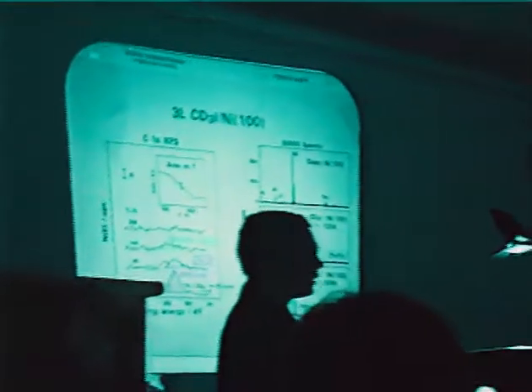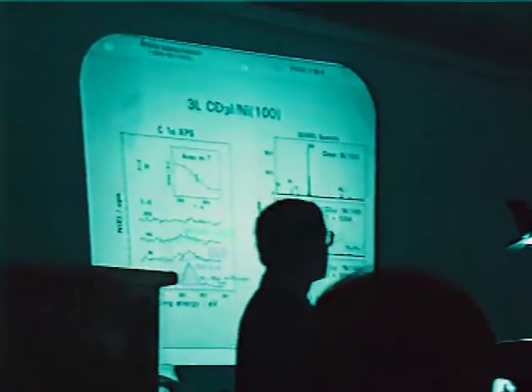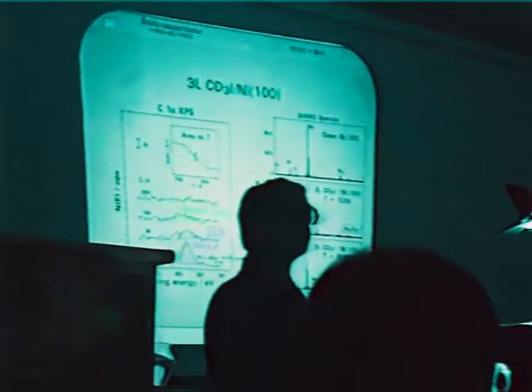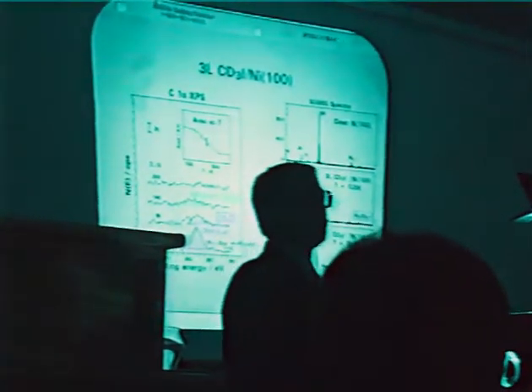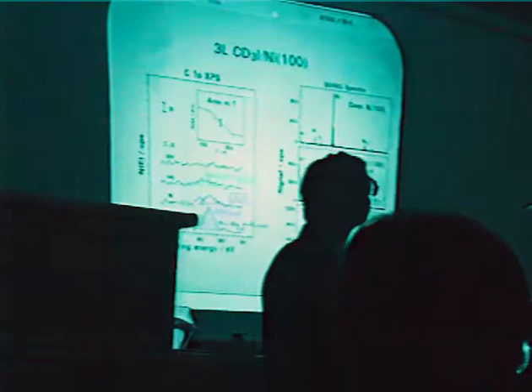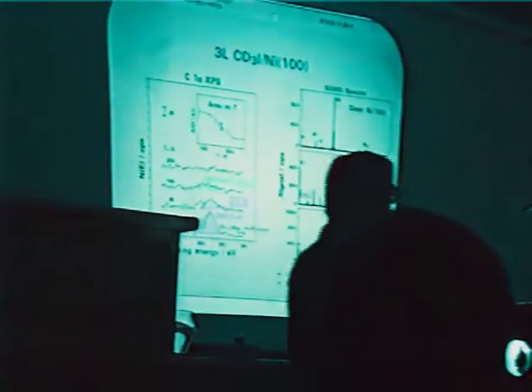And you see that signal actually goes down with temperature because of the formation of methane. So these two pieces of evidence, together with some other arguments that I'm going to give you later on, and the fact that we have seen methyl groups on other surfaces by, for instance, reflection absorption infrared spectroscopy, make us quite confident that we actually make methyl groups. I also will try to point out a little bit later on that we only form methyl groups below 200 degrees Kelvin. We do not see any more dehydrogenated species. We don't see CH2s. We don't see CH groups, just CH3s.